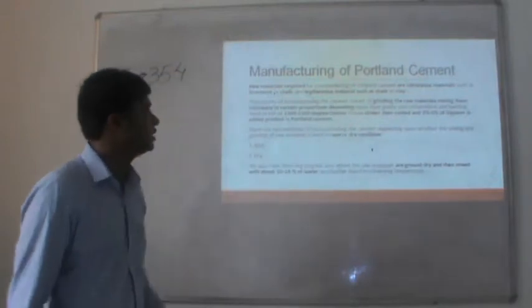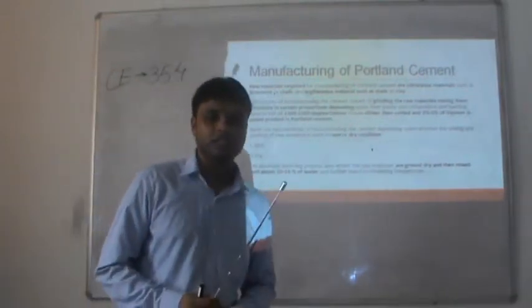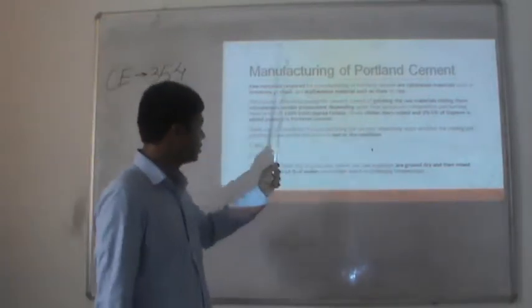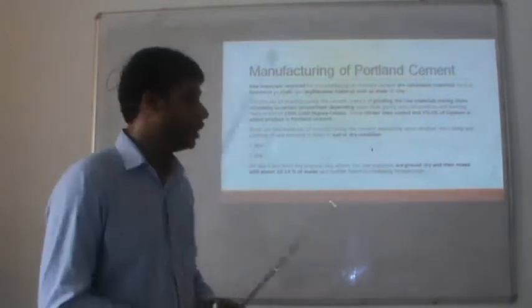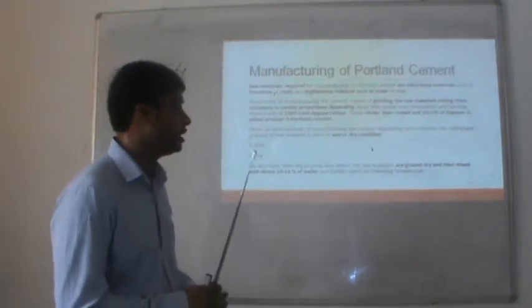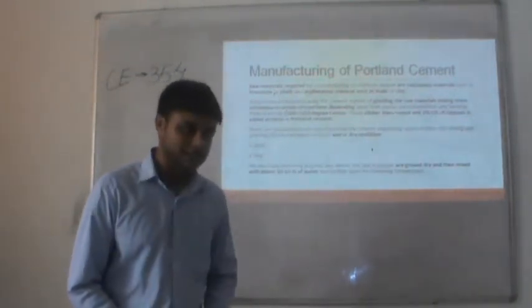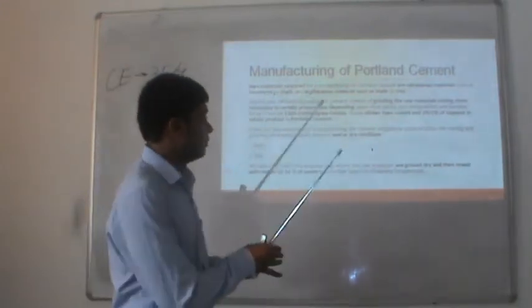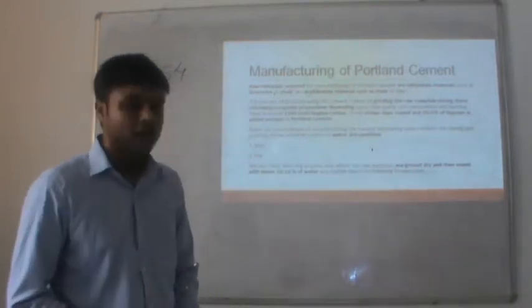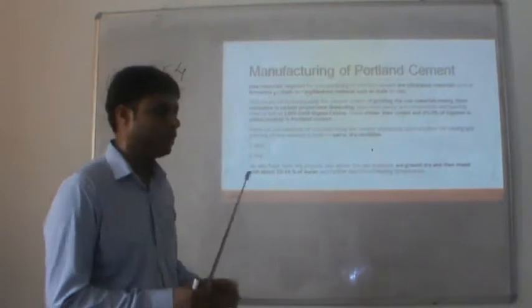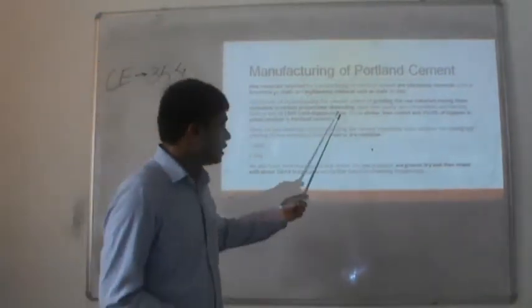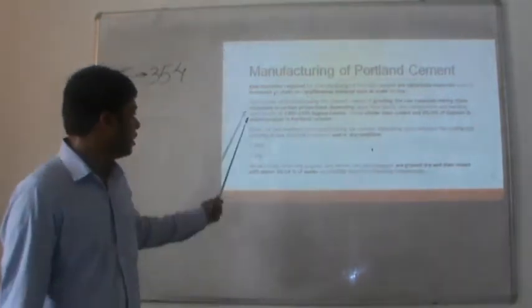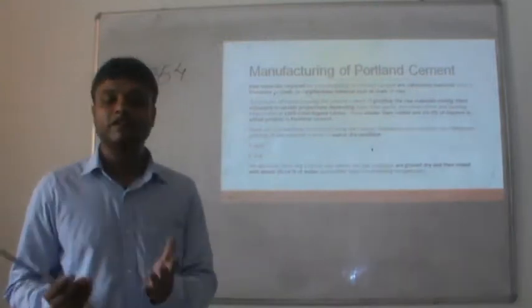The manufacturing process consists of grinding the raw material first, then intimate mixing of calcareous and argillaceous materials, and then feeding that intimate mixture into a kiln maintained at 1300 to 1500 degrees Celsius. The output comes out in the form of clinkers, which are then ground and further mixed with 3 to 5% gypsum to form the final cement.